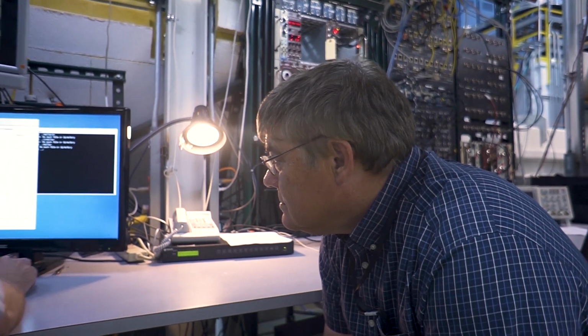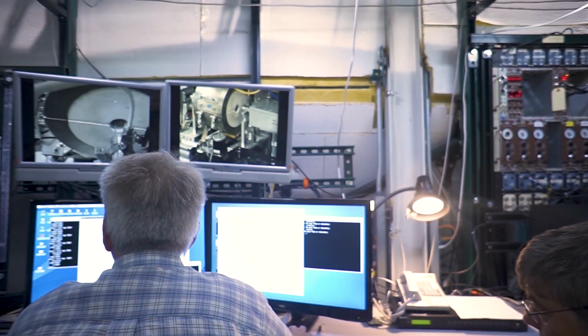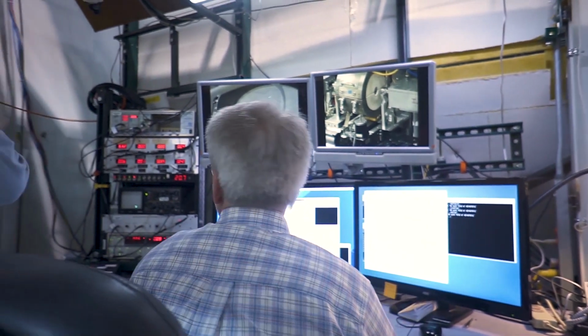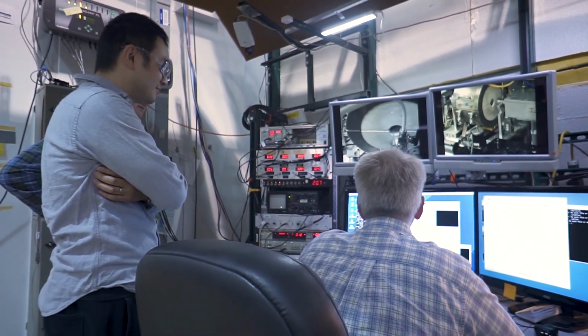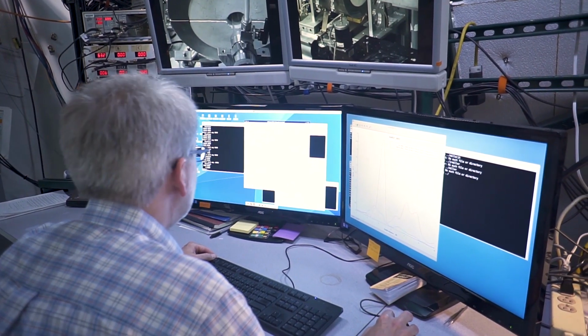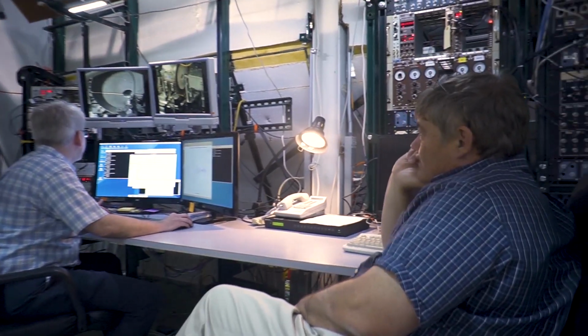In-situ and operando techniques allow us to monitor how the catalyst changes with time to understand which factors are governing the deactivation. Then using this information, we can develop regeneration processes such as steam stripping to remove carbon deposition, a major cause of catalyst deactivation in biofuel processing. So by understanding what the effect of the regeneration process is, again, we can help tailor synthesis processes to address any issues that the regeneration process may create.